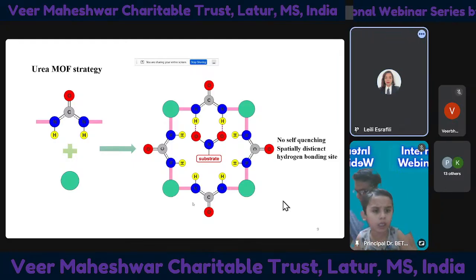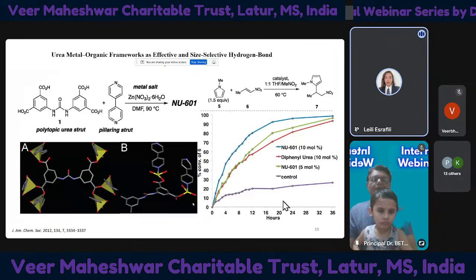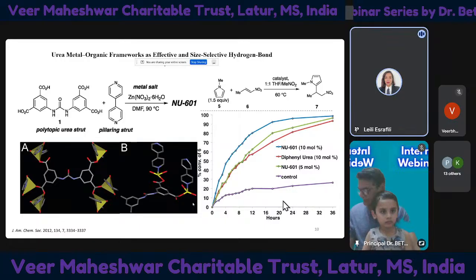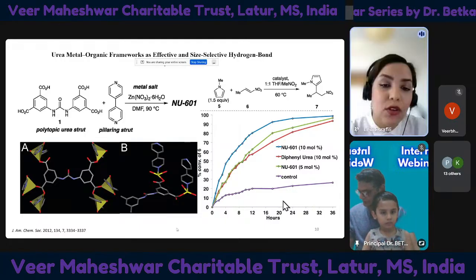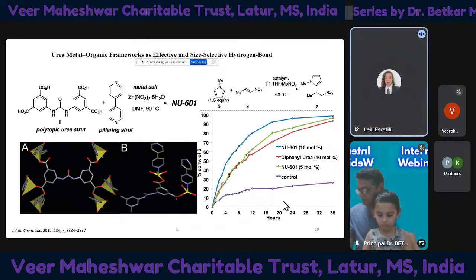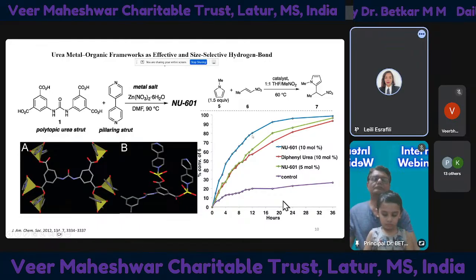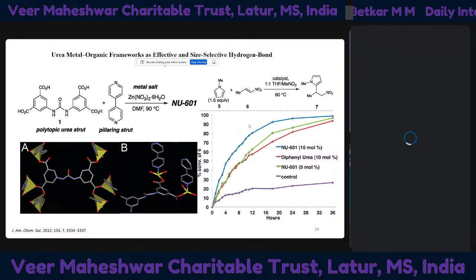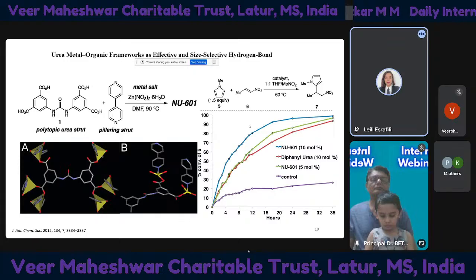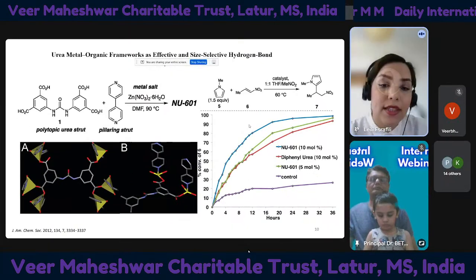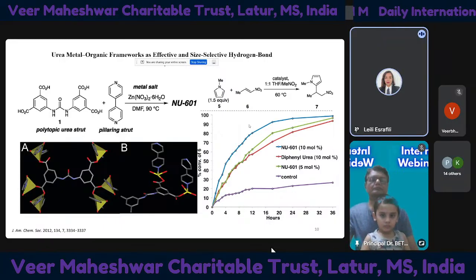To propagate the reaction. The first example of a urea-based MOF was reported by the Northwestern University group, especially by Omar Farha and Joseph Hupp. They synthesized NU-601 and used it as a catalyst for the Friedel-Crafts reaction between pyrroles and nitroalkenes. The MOF showed higher catalytic activity compared to free linkers. However, stability was a major limitation in this work. The structure collapsed after removing solvent molecules, which here was DMF, because DMF itself has an amide group and can strongly interact with the urea, and this made the urea group less active because it was in direct competition with the solvent molecule.